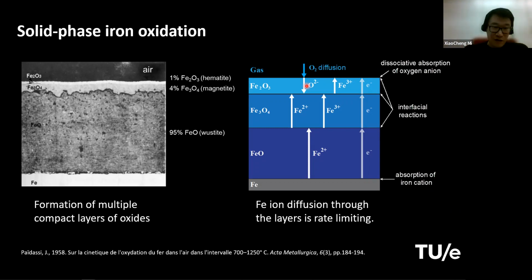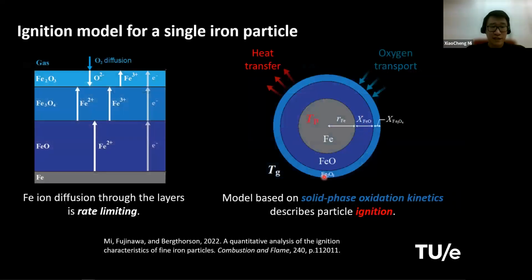So this overall oxidation process is mainly limited by the rate of Fe ion diffusion through these two thicker layers. And FeO layer is definitely thicker, so Fe ion diffusion through this layer is the rate limiting step. And then we can just take this idea and wrap these layers around to build our single particle model for solid phase oxidation, and use this to study the ignition characteristics of iron particle.